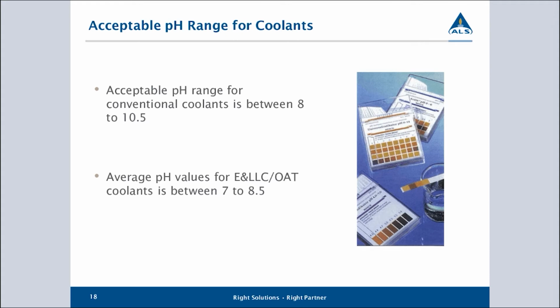For your longer life or your hybrid coolants, generally they're running between the range of 7 to 8.5, and more typically around the value of about 8 would be a typical value of what you see for the coolant pH. And as I say, ideally, whatever its starting value is, it should remain at that value. We don't want to see changes in the coolant over time.